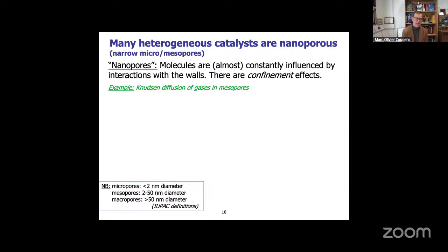I think the terminology really depends on how molecules interact with the environment, with the pore. So if you're a hydrogen molecule in a pore that's 50 nanometers wide, it may behave very much as in the bulk, but things depend also on its mean free path of these molecules. So whether something is affected by its environment really depends on things like the pressure, on the conditions, and on the ratio between the size of the molecular probe and the size of these pores. So I would like to say that a nanopore for me is where molecules are almost constantly influenced by interactions with the walls, so that there are confinement effects. And so we certainly have this in micropores, less than 2 nanometer diameter, but we often have this as well in mesopores, from 2 to 50 nanometer. So an example is Knudsen diffusion of gases in mesopores.